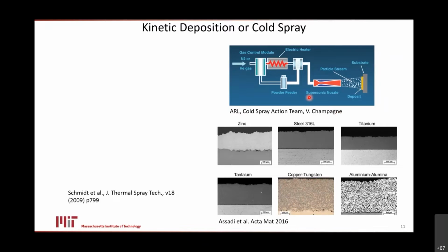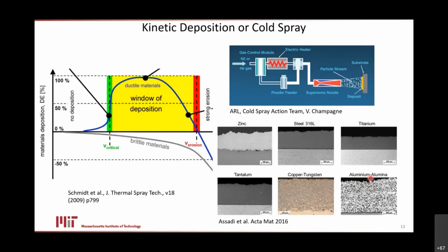The reason is that when metal gets flying that fast, upon impact there's so much plasticity that you can actually get particles to stick and grow a coating by virtue of their kinetic energy alone. So you don't even really need to heat these things. You can heat them mildly, but you don't melt them. You just literally spray solid particles, stick them, and grow them into coatings. And you can do it for lots of different metals and composites. And this really is a technology that is taking off, and it's becoming quite a large industry now.